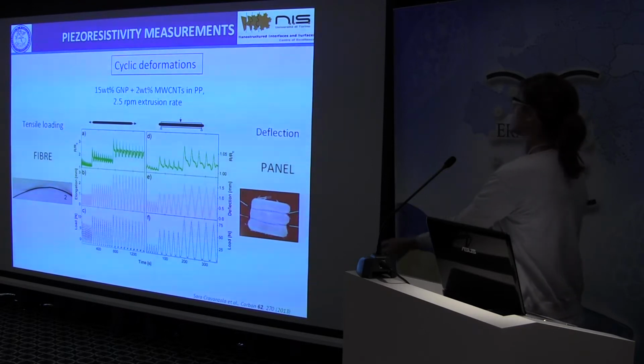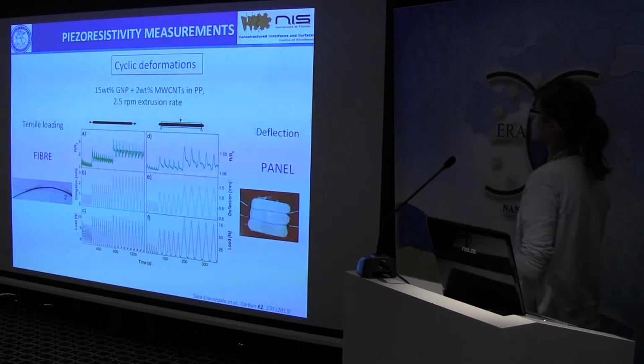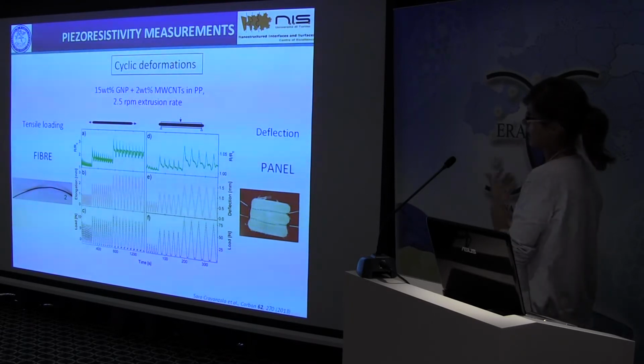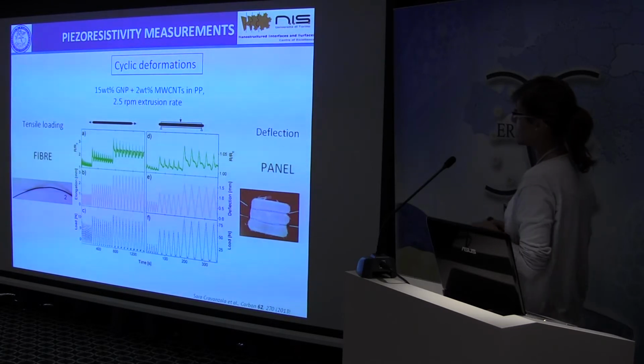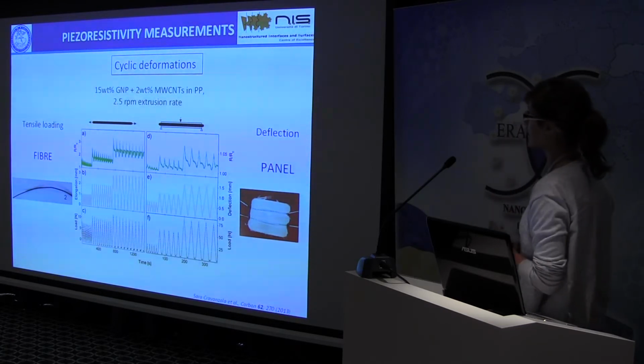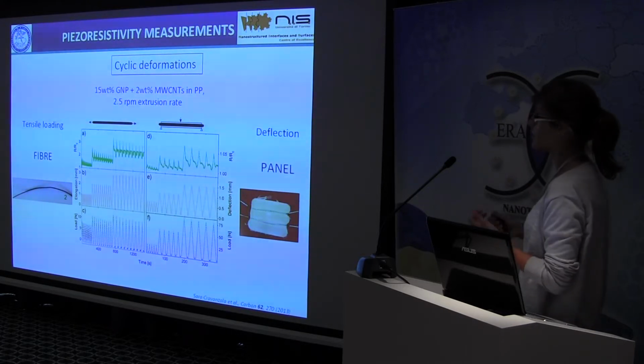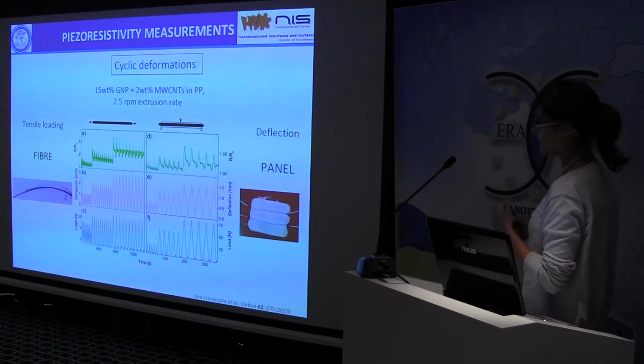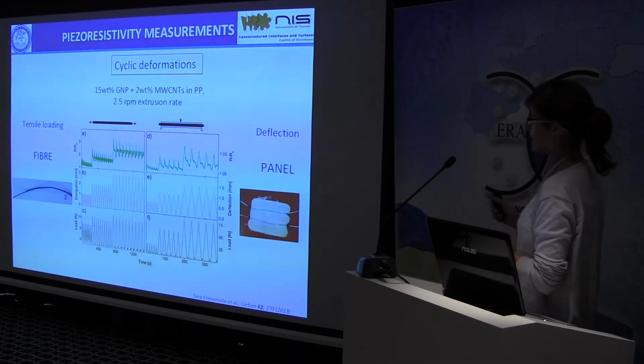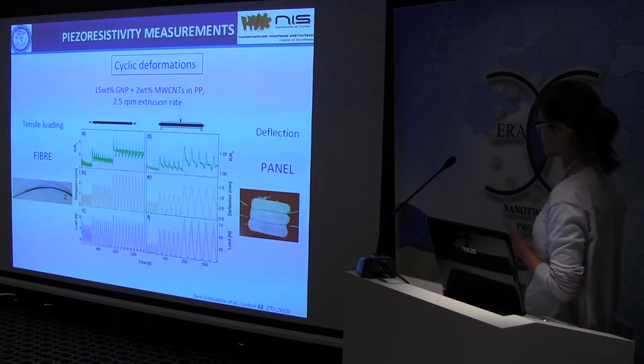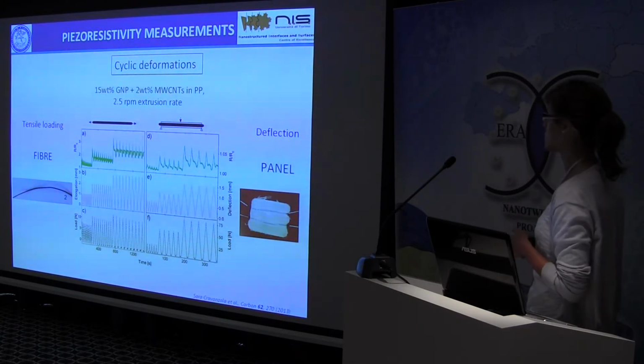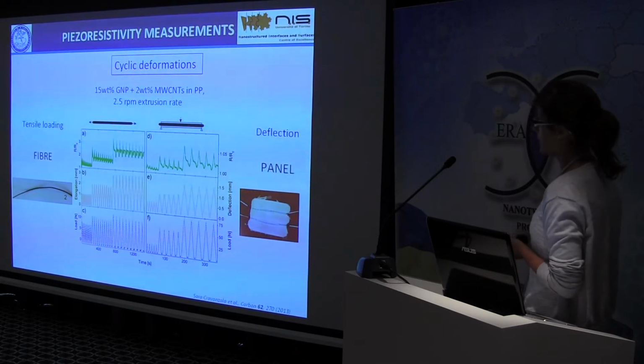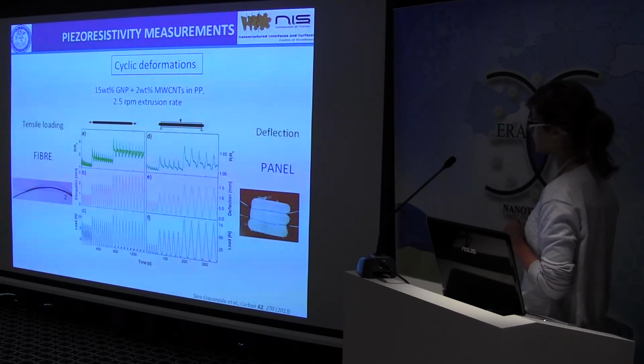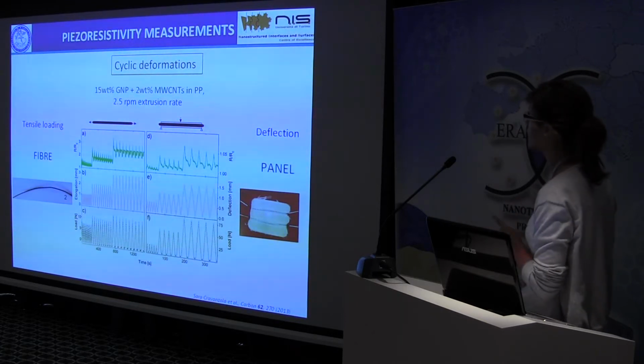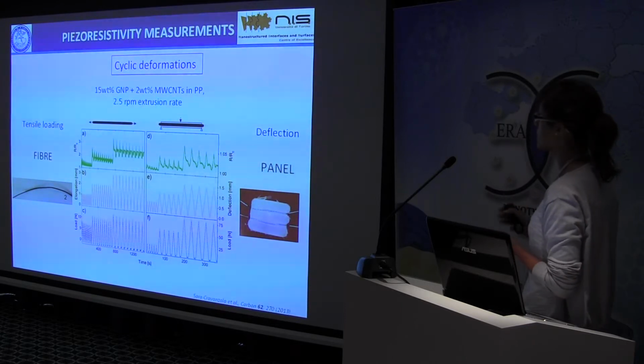Then the composites containing both multi-walled carbon nanotubes and graphite nanoplatelets were analyzed to see if they are piezoresistive. So a fiber, as it is, was subjected to a cyclic deformation, in particular a tensile loading. After that, the same kind of fiber was embedded in a polypropylene panel to create a piezoresistive sensor, and this panel was subjected to cyclic deflections. Here you can see how the loading, the elongation for the fiber, and the deflection for the panel, and the resistance change during the deformations.